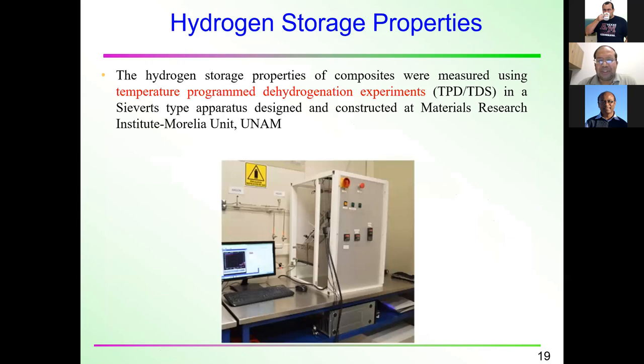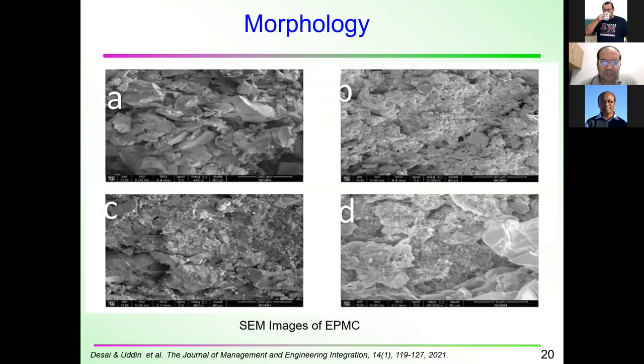Then I tested this material. I used TPD or TDS, which is a temperature programmed dehydrogenation experiment. I tested its hydrogen storage capacity and hydrogen release capacity. This diagram is showing some SEM images. Basically, it's a polymer network with metal hydride and carbon nanoparticles.